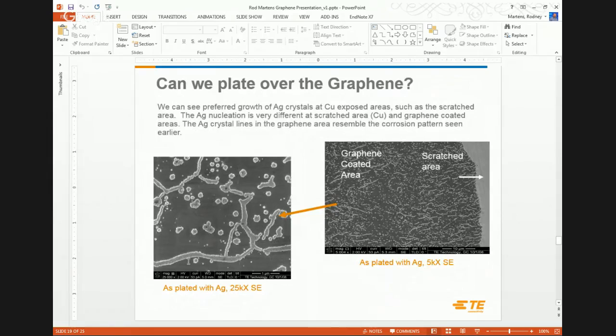Now, that's interesting. Can we make lemonade out of the lemons here? So previously that was a corrosion response. What I'm showing here is a plating response. So we took a silver strike bath to see if we could initiate plating through the graphene, and similar to the corrosion, we can initiate plating at the grain boundaries.